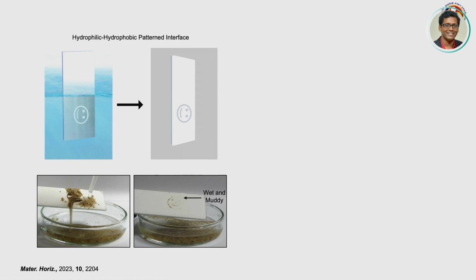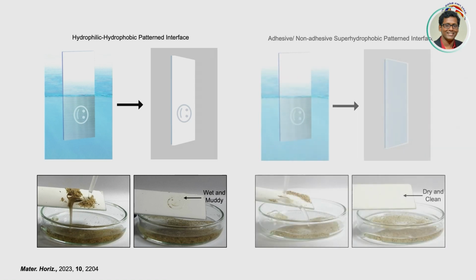Now, just to summarize this particular work and precisely tell what is the difference between a conventional hydrophilic, hydrophobic, or hydrophilic superhydrophobic pattern versus this adhesive, non-adhesive superhydrophobic pattern: these conventional interfaces are good for many applications, but they can easily get fouled when you expose them to dirt, dust and water, because water integrates precisely on the hydrophilic domain. Whereas these particular interfaces are extremely water repellent, whether adhesive or non-adhesive. So they never get wet, and they are self-cleaning all the time. So for outdoor applications, for these kinds of anti-counterfeiting applications, these interfaces will be much more desirable. And these are a rare design which can only be achieved through this simple chemical modification.